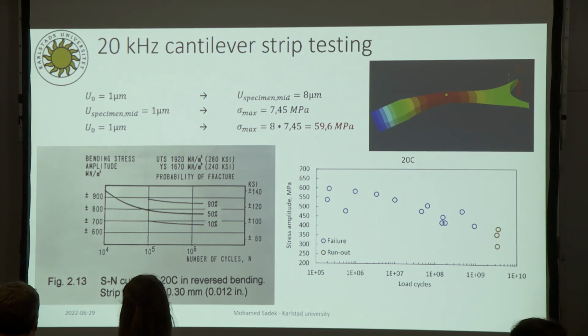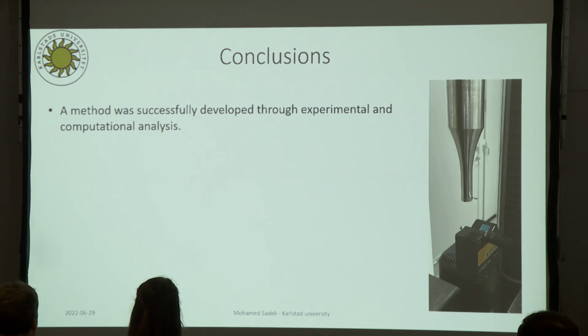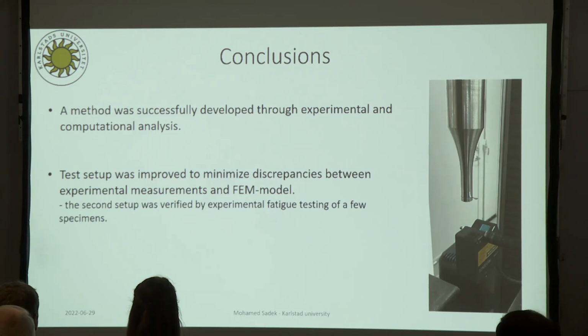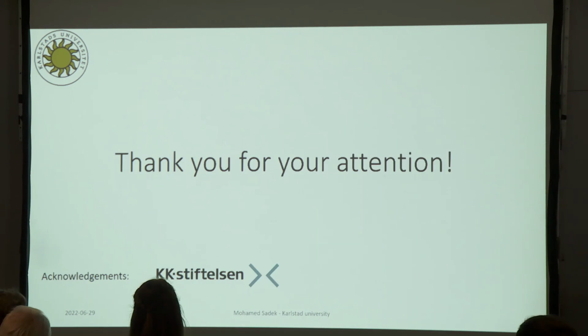Anyhow, as I said, we will retest the material with the new specimen. We will be able to compare it to these old values. So a method was successfully developed for testing strip steels, and it was successfully improved to get rid of discrepancies. And the new horn was actually tested with a few specimens, and the specimens were successfully failed in fatigue failure. Thank you for your attention.